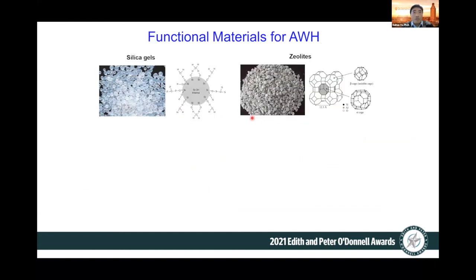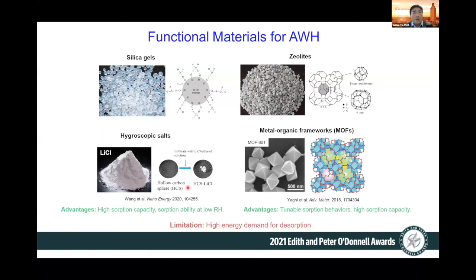So typically, there are several types of functional materials for moisture absorption for atmosphere water harvesting, for example, silica gels, which are porous materials, zeolites, or hygroscopic salts such as lithium salt, or other metal compounds. And very recently, metal organic framework materials have also been explored for atmosphere water harvesting. Due to their highly tunable structure between the metal ions and the organic ligands, they can offer tunable pore size and pore volume to have tunable absorption behavior. So they can actually have a high absorption capacity at extremely low relative humidity. But one of the limitations for all these different types of material is that when you talk about releasing water, you need to pay a penalty, because high affinity to the water also means that when you want to release the water, you need high energy to release it. So you need a delicate balance between these two.